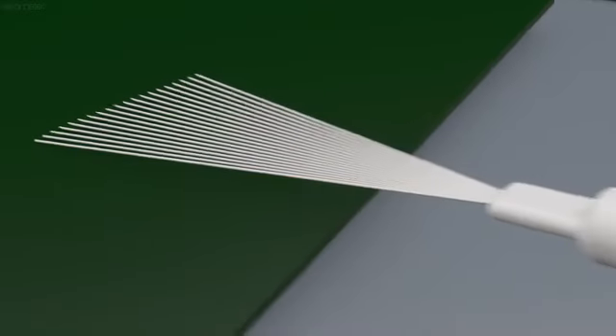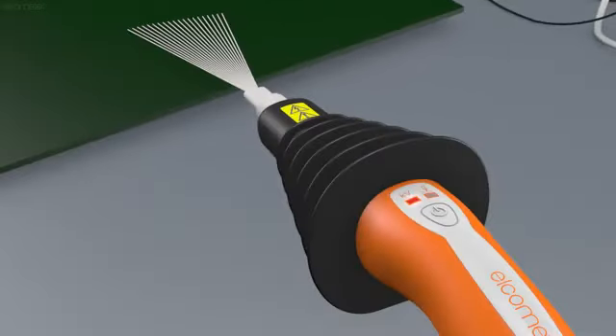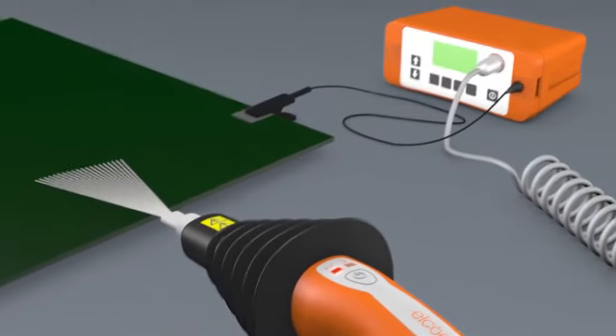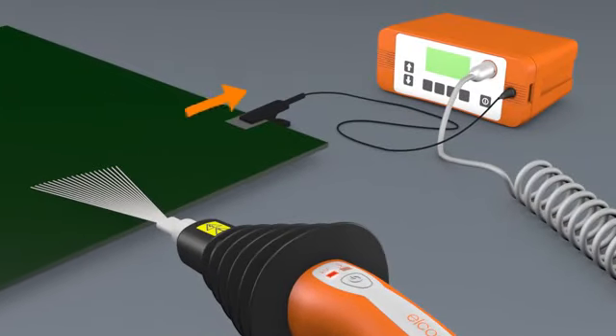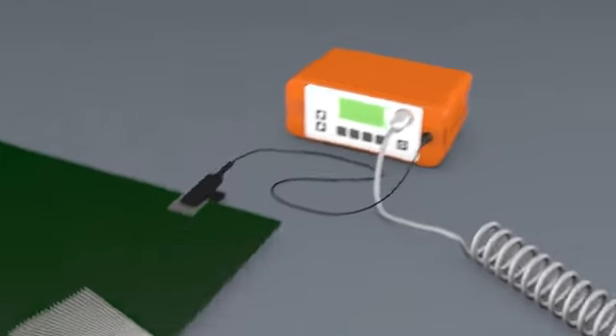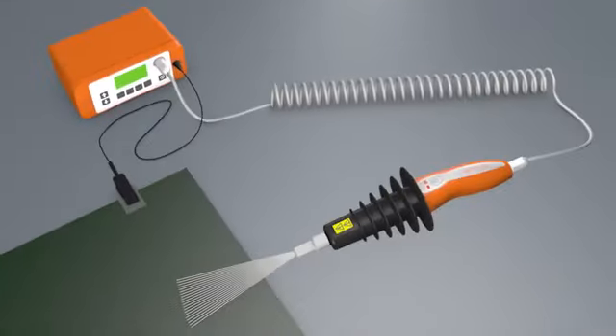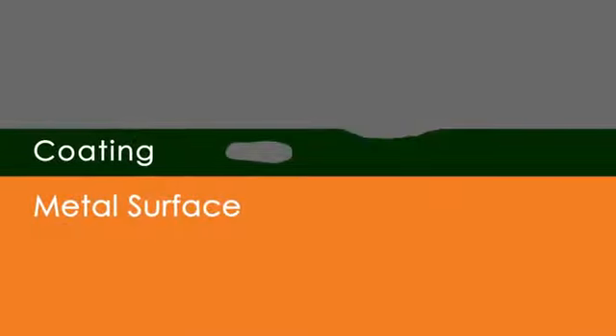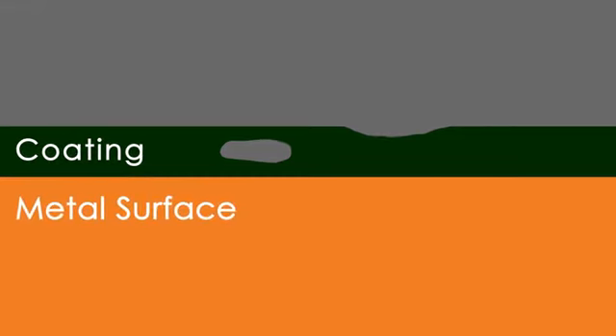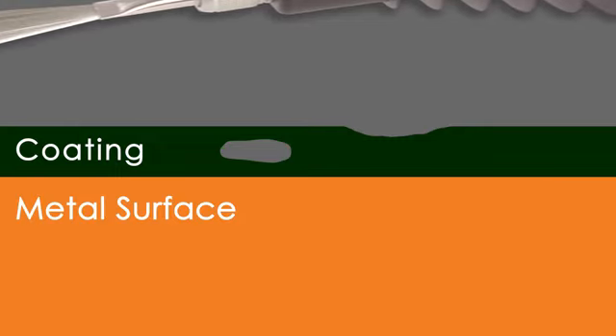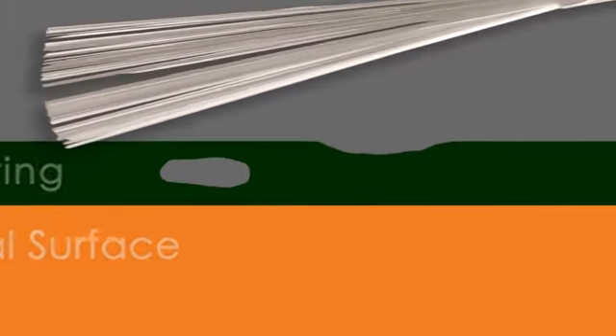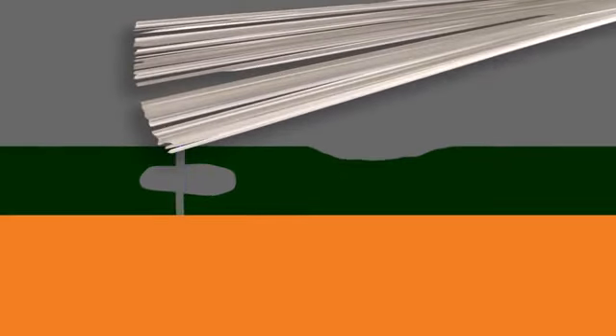When this breakdown occurs, the current flows from the probe, through the substrate, and back into the holiday detector, via a grounding cable which is clipped to an uncoated section of the substrate being tested, completing a circuit. This instantly triggers an alarm to signal a flaw has been detected. As the high voltage method can locate any area where the coating is weaker than specified, this allows you to detect flaws that don't go all the way down to the substrate, as well as voids within the coating.